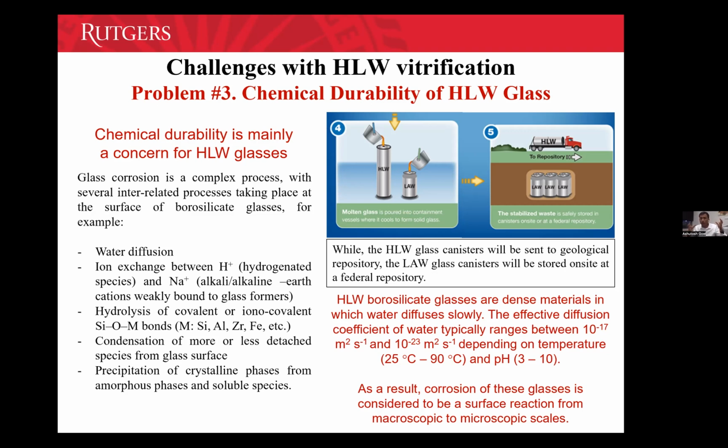So now it will not be only water. Think about it. It will also be all the sand, all the concrete, all the steel which was around it, everything. So the pH of the water will not be the pH of pure water. We are talking about alkaline pH, or neutral to alkaline pH, right? Or it can even go to hyperalkaline pH, depending upon what kind of repository we build over there.